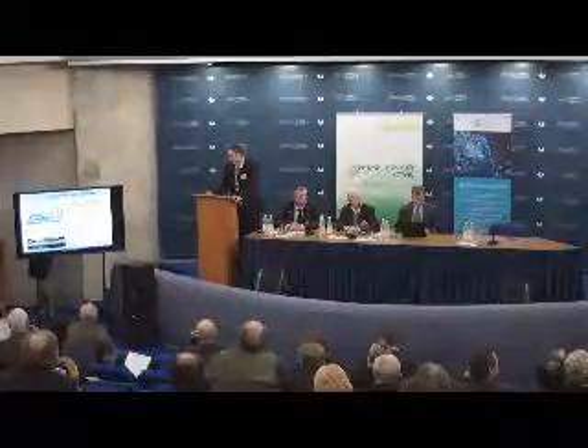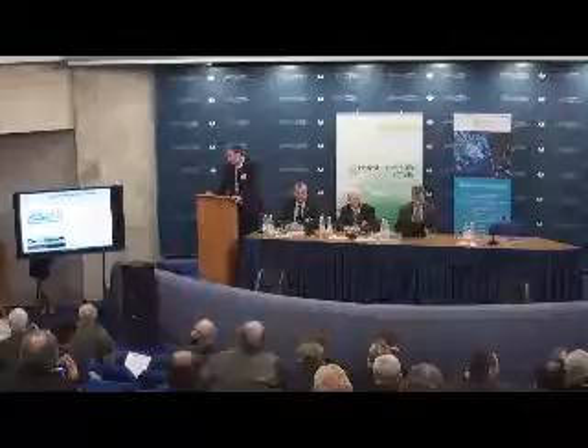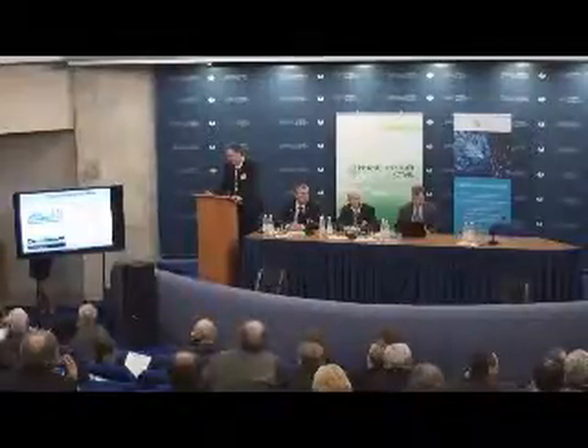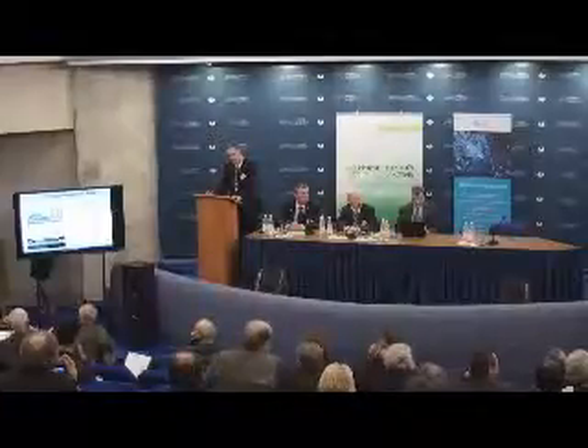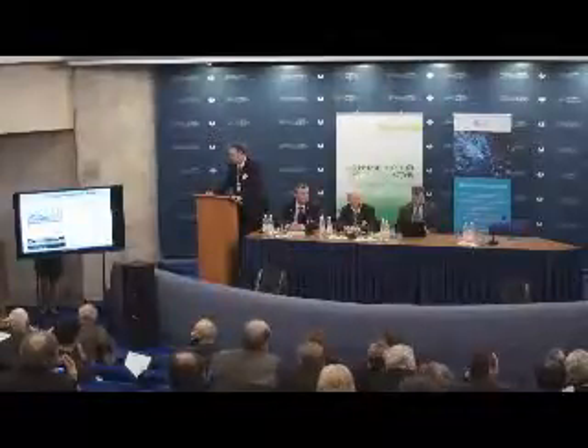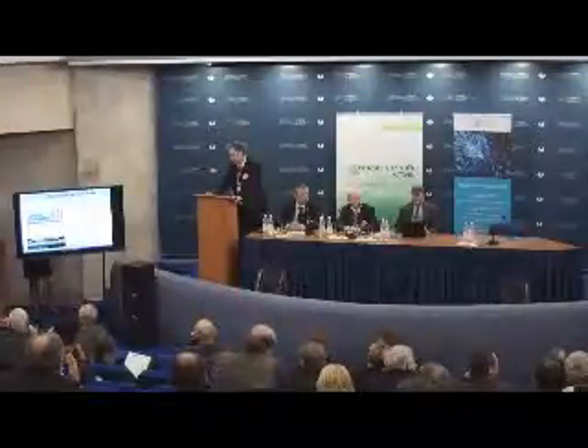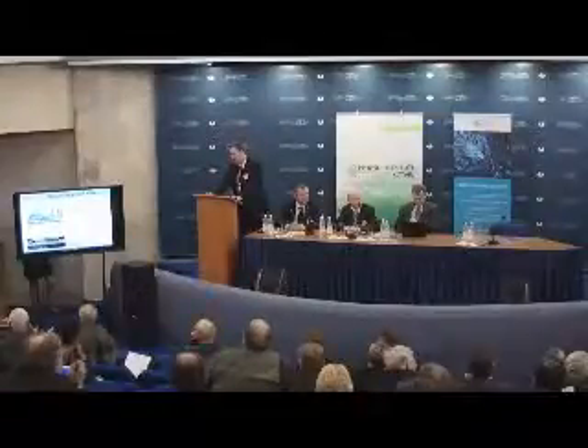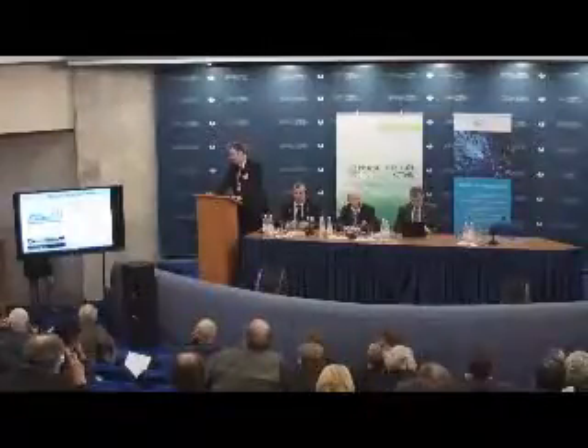Then the read heads, ALD is the only film that can reach 10 megavolt per centimeter around the corner, coating into the gaps and passivation of the read head in the hard drives. So we were told by a hard drive manufacturer that ALD technology more or less saved the whole industry, because they were facing a brick wall which they couldn't break otherwise.